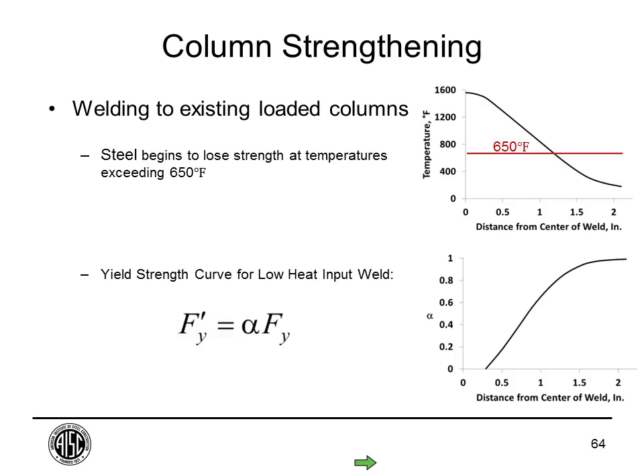Another thing to consider, which I mentioned previously, but it's particularly relevant when looking at columns, is that the temperature is going to exceed 650 degrees, and at that temperature the steel will begin to lose strength. So taking a look at this chart, you can see that this is the temperature of the steel at a distance away from a 1/4 inch weld along the length of a member. So you can see that portions of steel within about 1 inch to 1.5 inches away are going to exceed that temperature and begin to lose strength.